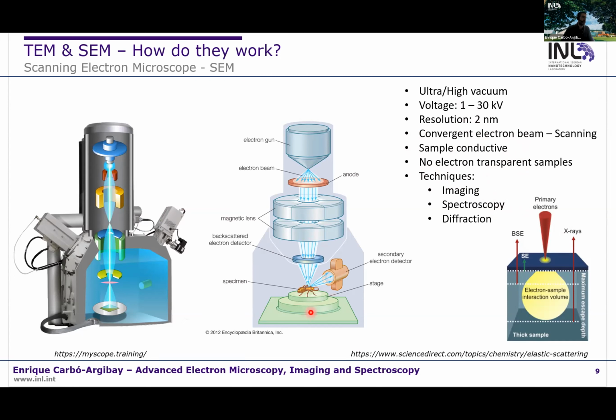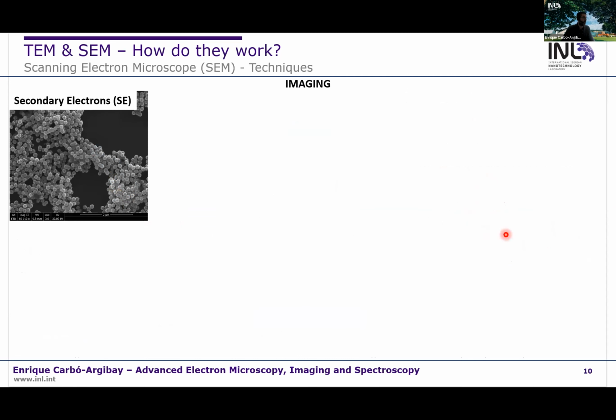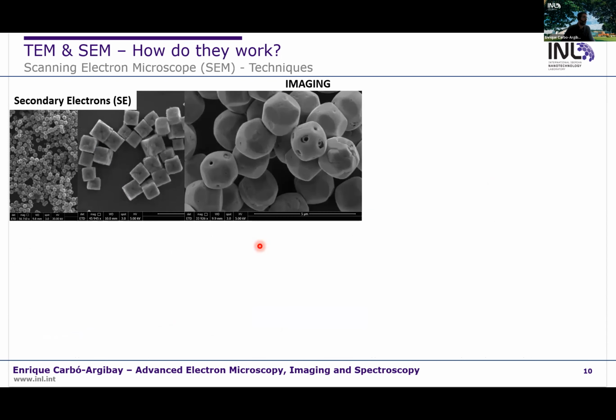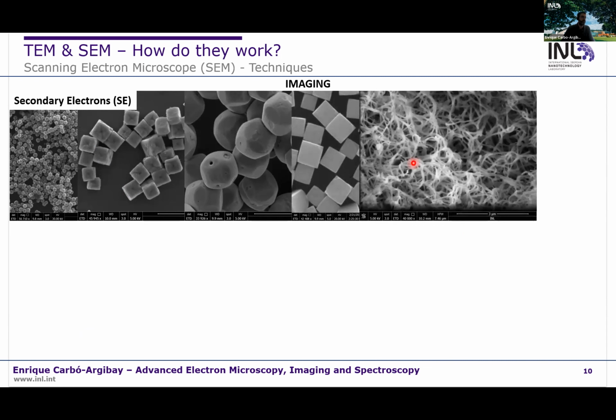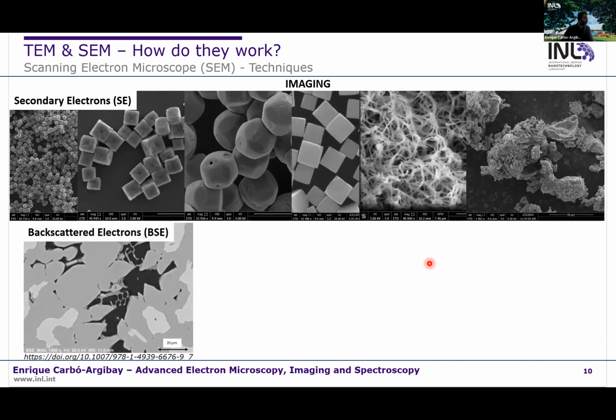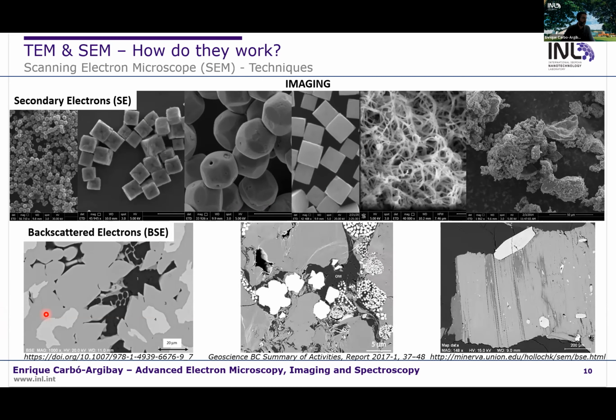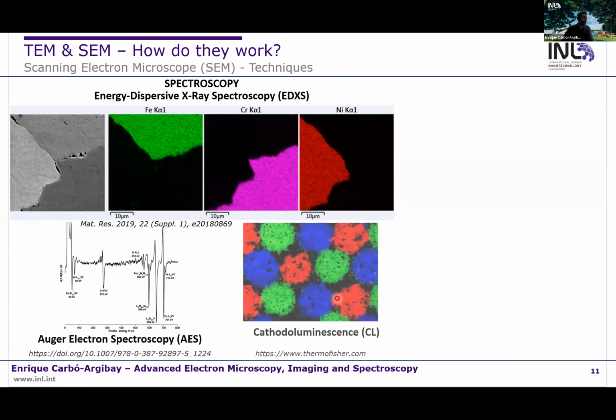And the information we can get from the sample in this case can be an image, a spectrum, or a diffraction pattern. As you can see here, we can characterize different types of nanoparticles, catalysts, fibers, or even analyze cross sections of different materials. The different contrasts we can see here tell us that the sample has a different chemical composition, and this can be confirmed with spectroscopic techniques in the scanning electron microscope. So we can combine the imaging mode with the spectroscopic mode.